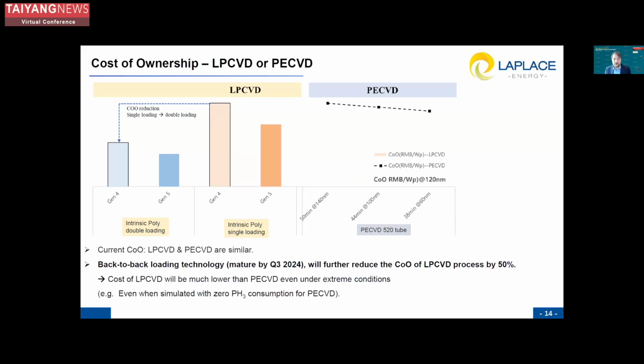When we look at the cost of ownership for LPCVD or PECVD, here we can see for our Gen 4 or our Gen 5 systems that we already currently, with our Gen 4 systems, are very similar between LPCVD and PECVD. While when we include our back-to-back loading technology, which will be mature and finally tested by Q3 2024 to be delivered, then we can further reduce the COO of LPCVD by about 50%, which brings it to a much cheaper system than a PECVD. And when we tried to simulate, we were not able to get to these numbers in the PECVD, even when we, for example, simulated with 0 phosphine consumption.